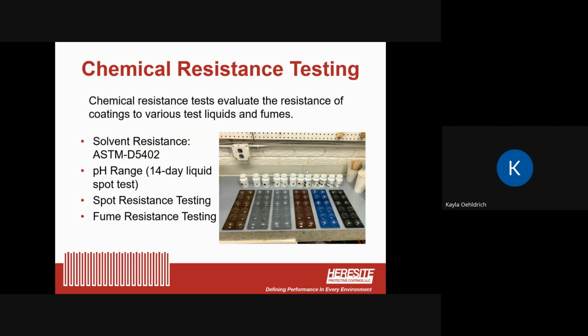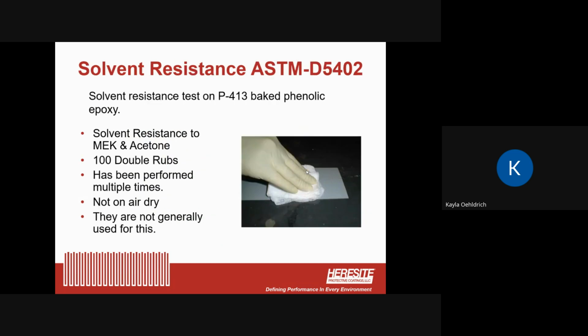So there are 4 basic tests that we do, categories of test to evaluate the chemical resistance of coatings with various liquids and fumes. And all of them are really important. The first one is the solvent resistance test. It's an ASTM test. We perform this on our P413 baked phenolic epoxy. It judges the solvent resistance to both MEK and acetone. Those are the 2 chemicals that are used. We do what are called 100 double rubs on it, which is forward and then back again. And then we evaluate the coating. So we may do that several times depending on what the coating is.